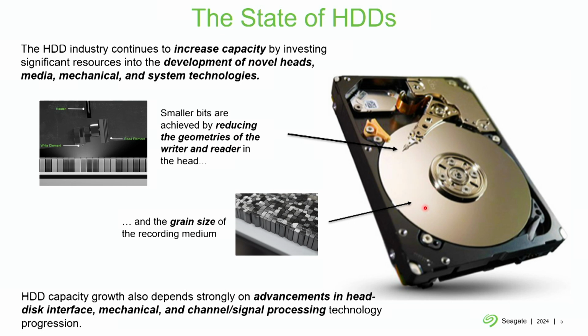The disk contains the storage medium, and it's made of a granular magnetic material. And these grains are on the order of less than 10 nanometers, and each bit is less than 10 grains. The distance between the head and the disk is on the order of a nanometer. And so this mechanical contraption has to ensure that there is on the order of 1 nanometer spacing in between the head and the disk.